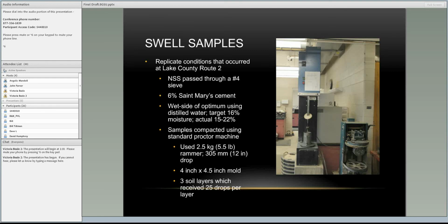And again, we used the ODOT facilities, the standard Proctor machine. The rammer was 2.5 kilograms with a 305 millimeter drop. The molds we made were 4 by 4.5 inches, and each sample involved 3 soil layers with 25 drops per layer. And we made a total of 12 samples, 4 samples per station, and to the right you can see the breakout of how these samples were designated.